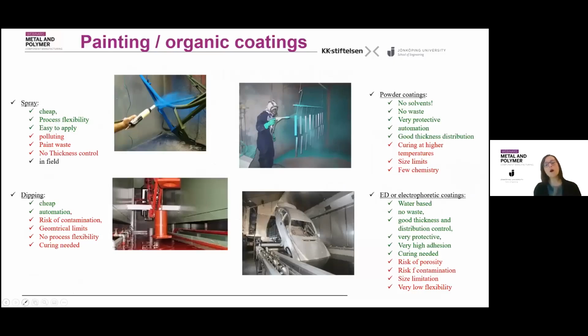Or you can go on water-based or non-solvent treatments, as powder coating or electrophoretic coatings. In that case, you have much more expensive treatments, but you avoid the use of solvents, you reduce the waste, and you create a very protective layer, because those applications usually need high temperature curing, so some temperature to create stronger bonding inside the coating and to the conversion layer beneath.